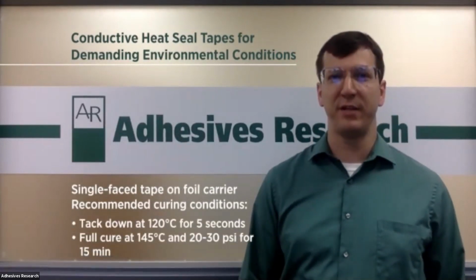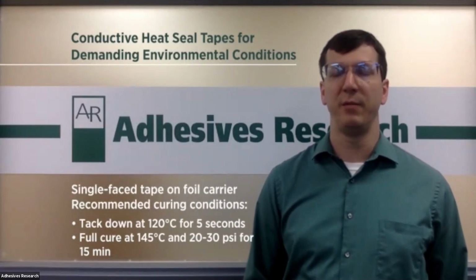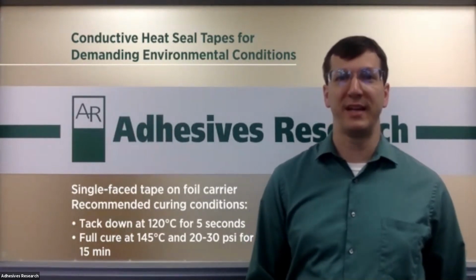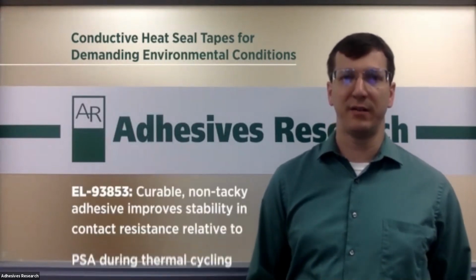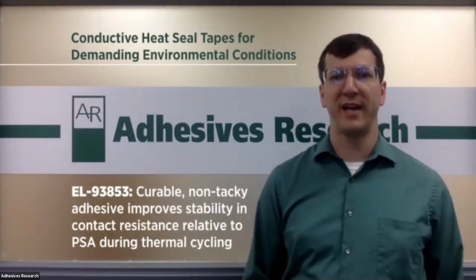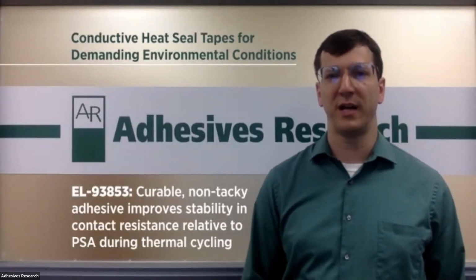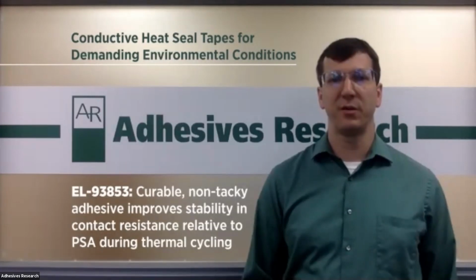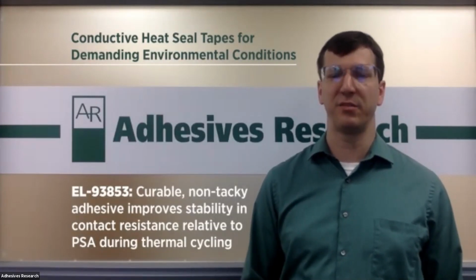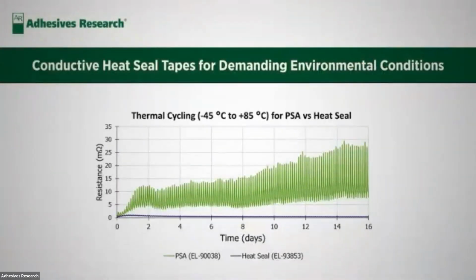Most of our PSAs are very well performing over a wide range of environmental conditions. However, some applications have very demanding temperature cycles and humidity cycles. In these applications, we recommend a heat seal adhesive, so specifically EL93853. This heat seal is non-tacky, needs to be cured after it is applied and laminated, but under temperature cycles provides much more stable contact resistance relative to the PSAs. You can see in the plot here on the slide that under thermal cycling from -45 to +85°C over 16 days, the heat seal adhesive has much more stable contact resistance than the pressure sensitive adhesive.